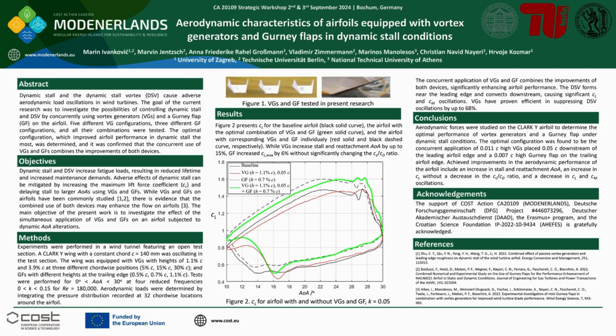To achieve the objectives of this research, wind tunnel experiments were performed on a constant chord wing that was equipped with 2 different sizes of vortex generators placed at 3 different locations on the airfoil, and 3 different sizes of Gurney flaps on the trailing edge. Experiments were performed for 4 different reduced frequencies between 0 and 0.15 and for Reynolds number 180,000. Aerodynamic loads were determined by numerical integration of pressure distribution recorded at 32 chord-wise locations.